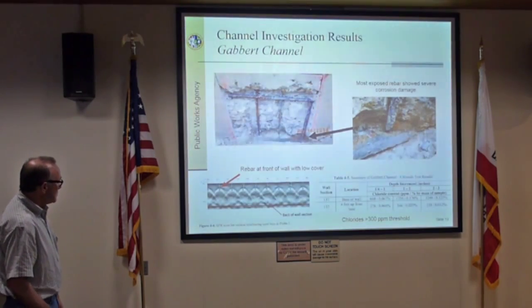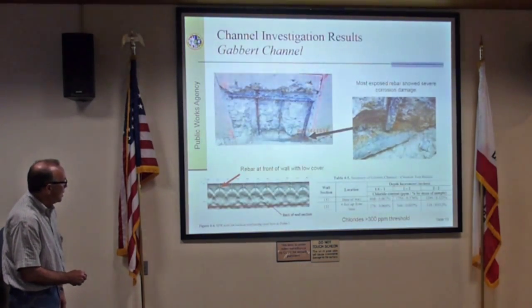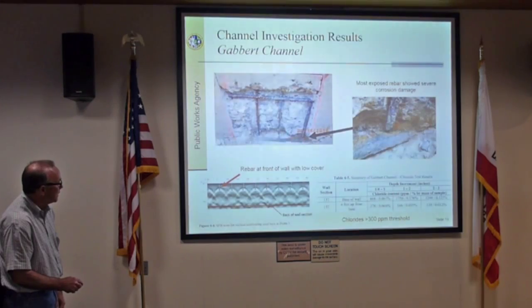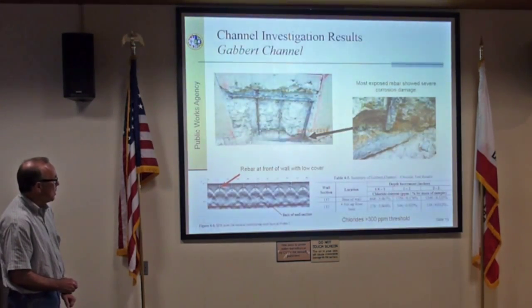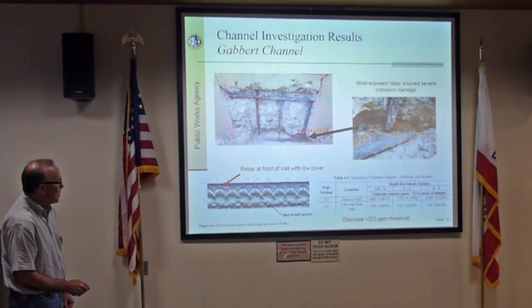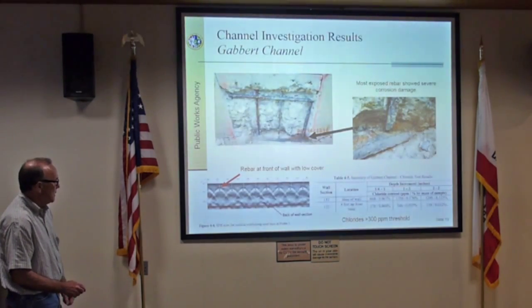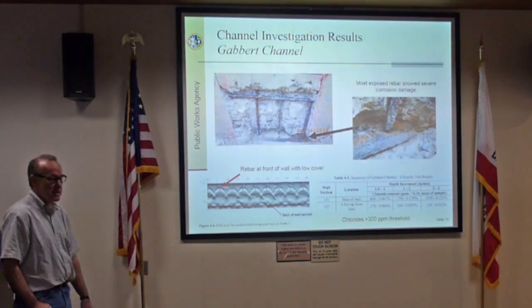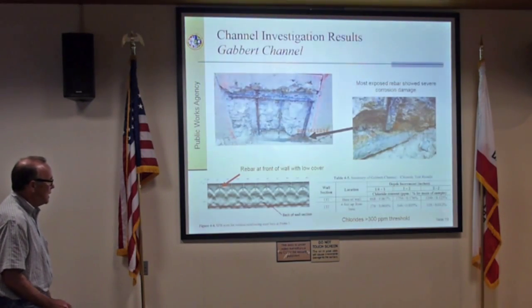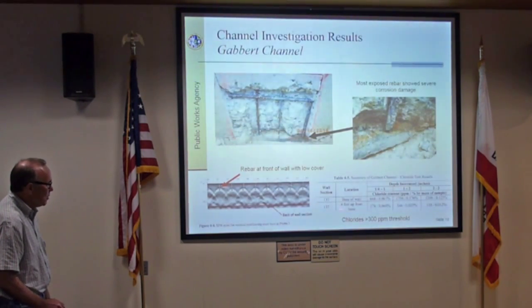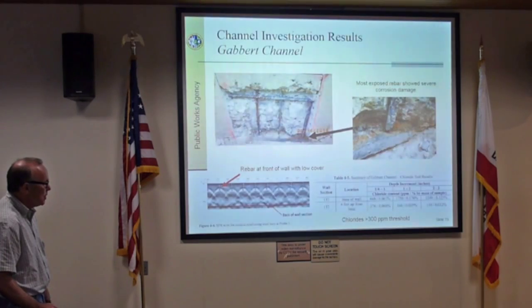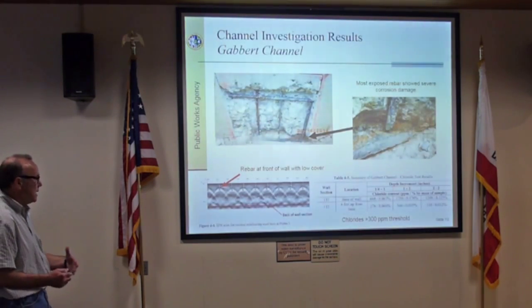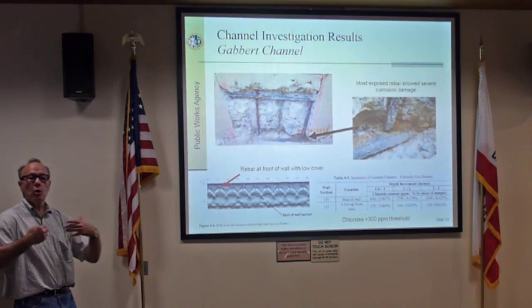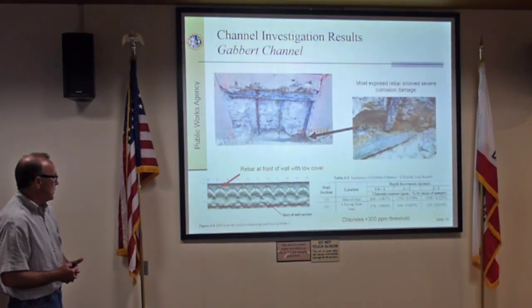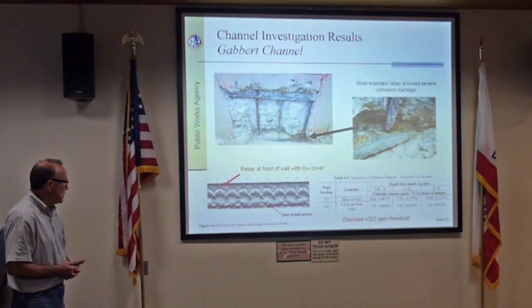Gabbert Channel, which was built along, you can see here, we got a corrosion product, very localized. The most exposed bars showed very severe corrosion very locally, but when you get away from that, it's very difficult to detect. This had a fair bit of chlorides. That chloride testing showed over 300 parts per million, which is the threshold value. So this is chloride-induced corrosion, which even further accelerates the corrosion process.